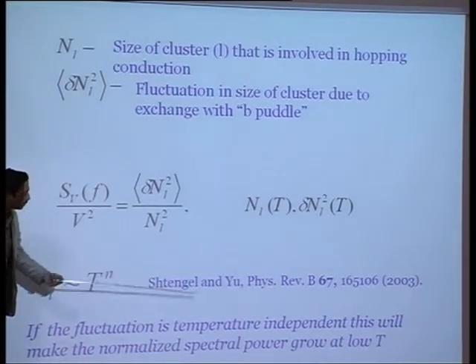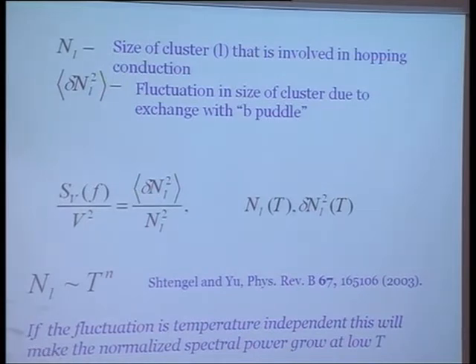There is a work done by Yu and Co. They have actually worked on percolating systems, and they found that the size of the cluster has a temperature dependence going as T to the power n.